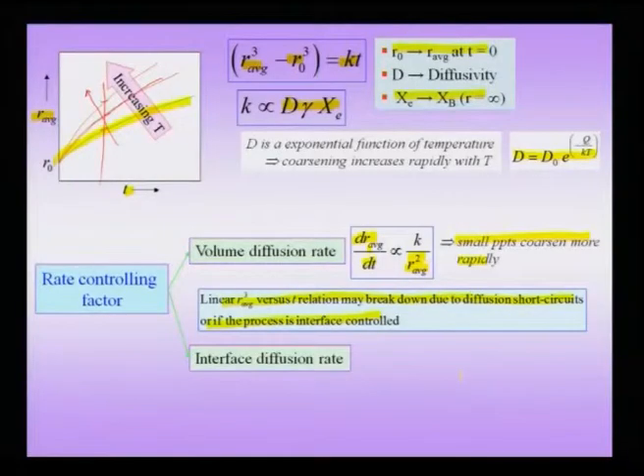With time, a fine distribution of precipitates that initially gave higher hardness will coarsen. The Frank-Read source operates around fine particles to give hardening. If the particles are coherent, dislocations can glide through them; if incoherent, dislocations go around the precipitates leaving dislocation loops — the Frank-Read or Orowan mechanism.